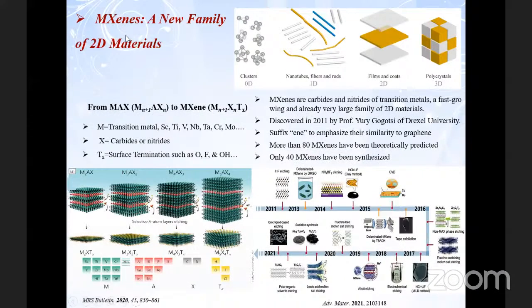What we are doing is working on MXene materials, two-dimensional materials, which are carbide and nitride two-dimensional materials. Here I have examples of thin film-like materials. We call them 2D materials. One of the famous and well-established materials is graphene. MXenes are carbide and nitride transition metal materials, and they have been a very fast-growing class of materials in the last 10 years. They were discovered very recently, in 2011, by Professor Yury Gogotsi, and till now more than 80 MXene materials have been theoretically predicted. But only a very limited number of MXene materials have been synthesized.